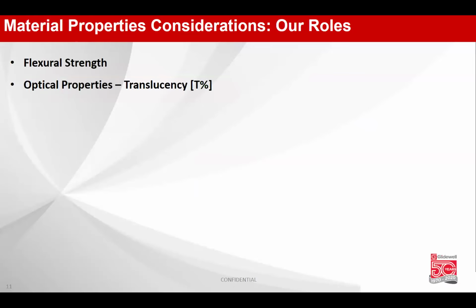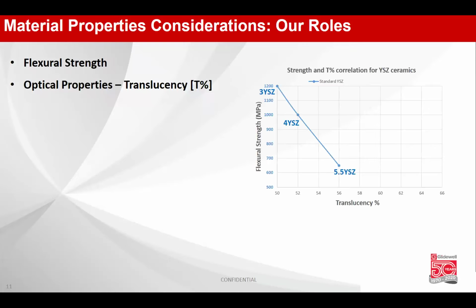So how are we getting this, right? Basically, there are two major properties into consideration over here. One is the flexural strength, and second is the optical property, that is the translucency. If you look at the regular YSZ ceramic in the market, you can see that it starts with 3Y, which has the highest strength possible, around 1200 MPa. And then as you increase the yttria level, the strength slowly decreases, but translucency improves. Why does that happen?